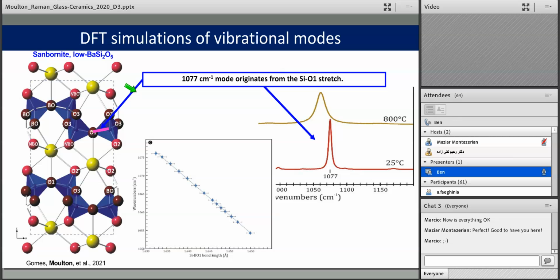I have done this simulation with some colleagues in Spain, and just to show you an example of a nice sharp vibration from our crystal sanbornite we saw a moment ago. I tracked this with temperature, and we knew how the thermal expansion of the crystal was. And so I was able to determine a very strong relationship between the Si-O1 bond length, this bond right here within the structure, as a function of temperature. So if you have simulations, it's really powerful because you can identify specific attributes within the structure, such as specific bonds, and create some empirical models of how they change with pressure, with temperature, or during other reactions.